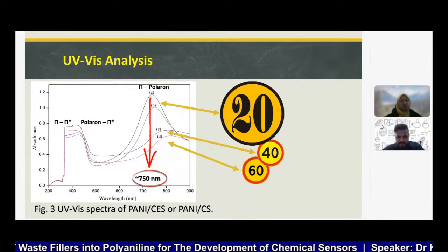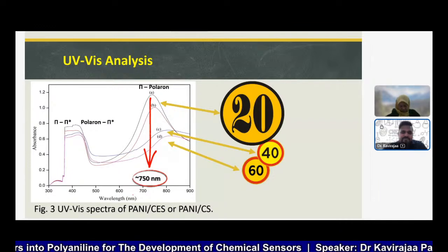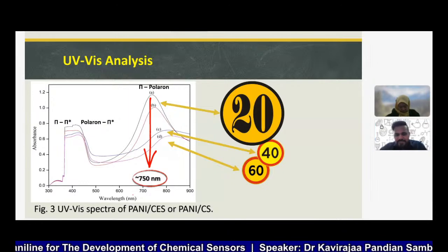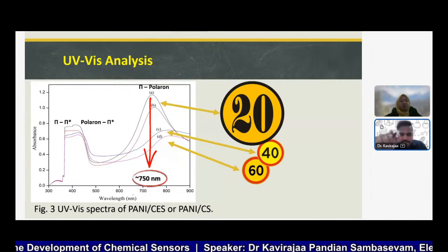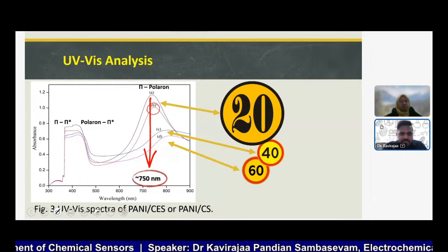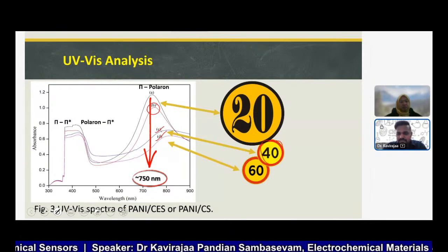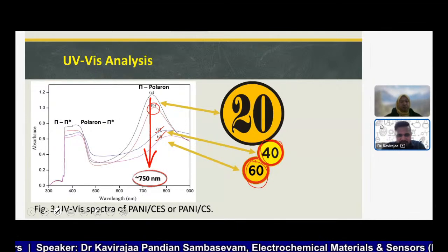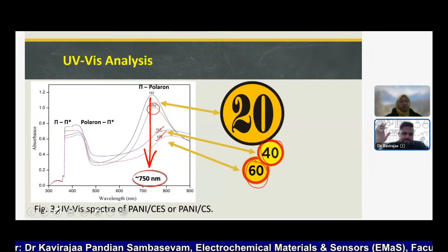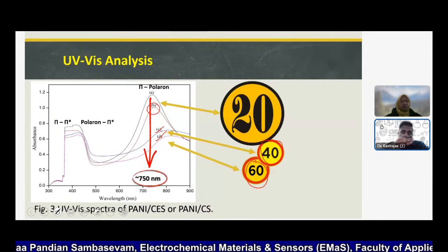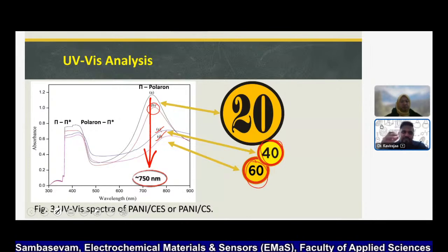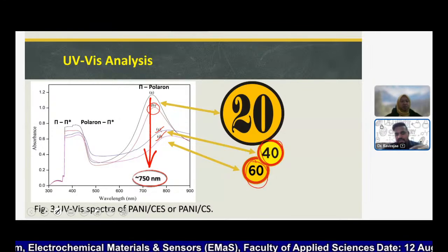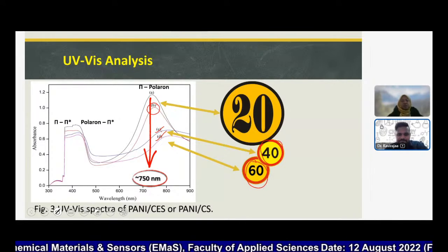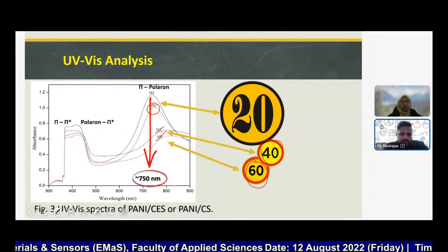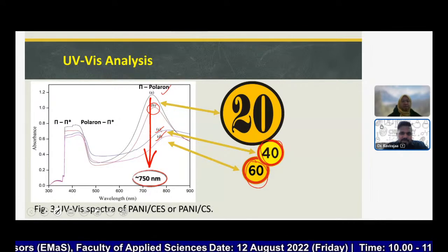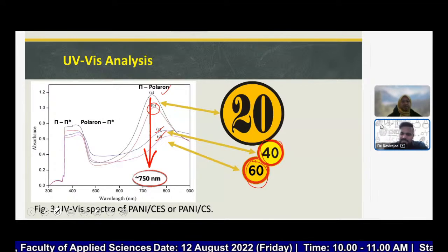So we also checked, after we add the filler, these shells, the polaron side. So what happens to the polaron side? Here the B is actually pristine polyaniline. But if we look at the C and D, this is the 40%, 60% ratio of the shells. I think this is kind of too much on the surface of polyaniline, which maybe blocked, I would say, the transport of electrons. Normally we use the term delocalization. Maybe when it's too much, it blocked the electron movement. So we don't get a good polaron absorbance over here. But for 20%, we actually got higher. But this thing we couldn't prove by using conductivity, because later I'll show the conductivity data.